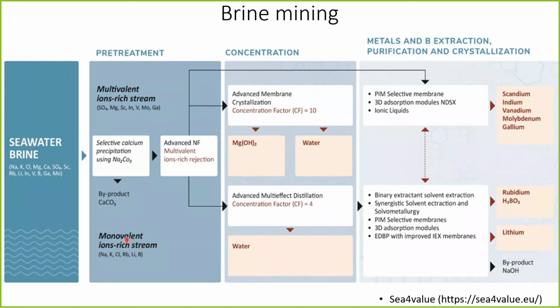If you look at the monovalent ions, you can use some advanced multi-effect distillation to produce further desalinated water, and then the remaining monovalent ions can be extracted further using solvent extraction, also the polymer ionic membrane and the 3D adsorption module, and electrodialysis with polymer-improved ion exchange membrane. Ultimately, we would like to collect rubidium, boron, lithium, or some other byproduct. So we can collect useful elements from brine, which can give extra income from the desalination plant, so that we can cover some of the very huge and expensive capital and OPEX cost.